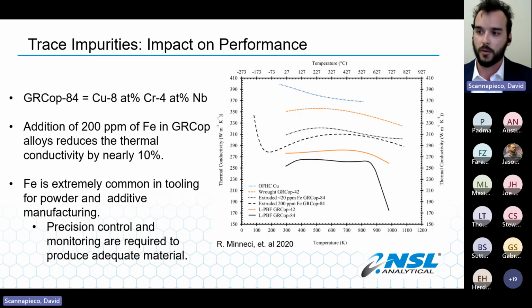Similarly, for one of the examples, GRCOP 84, which is a copper chrome niobium alloy, if it has just 200 ppm of iron, its conductivity reduces by 10%. This is for an alloy designed for its conductivity in combustion chambers, so this is a huge impact. So much so that NASA regulates that the GRCOP has to have less than 60 ppm of iron in it. And you might think iron is not that hard of an impurity to get in your material.